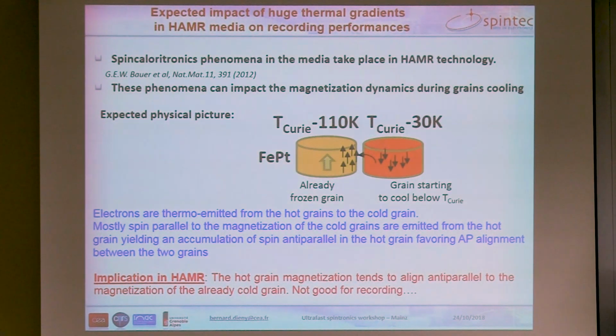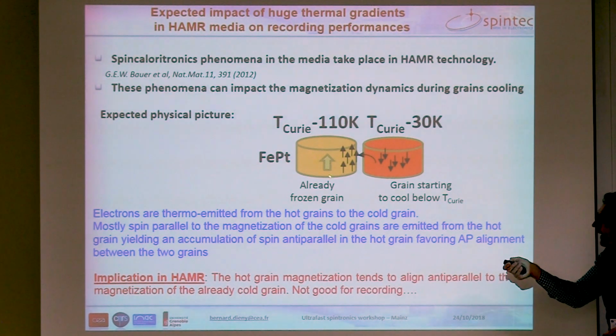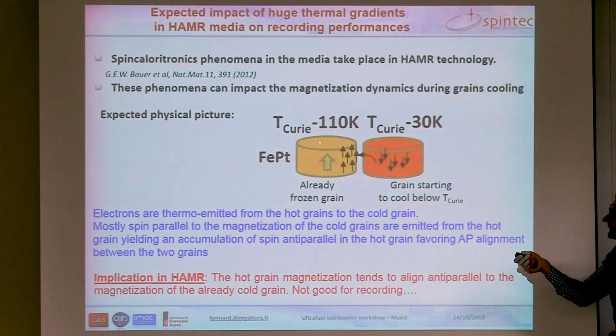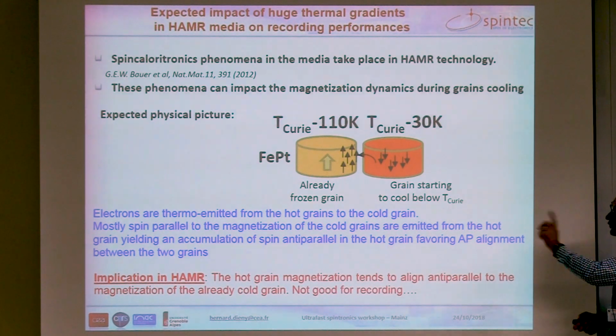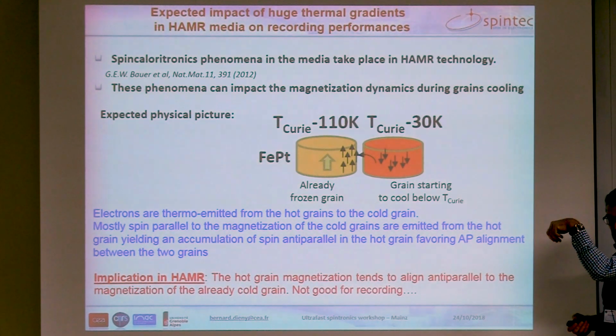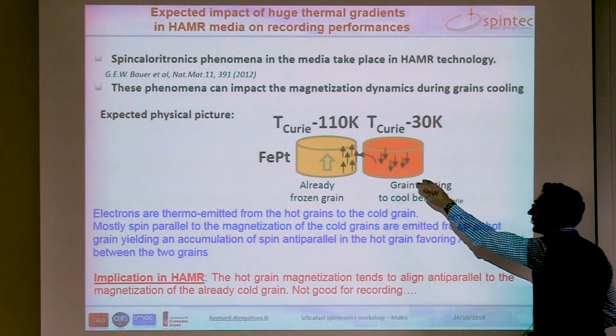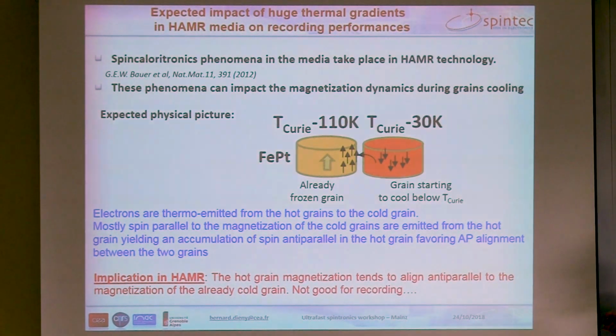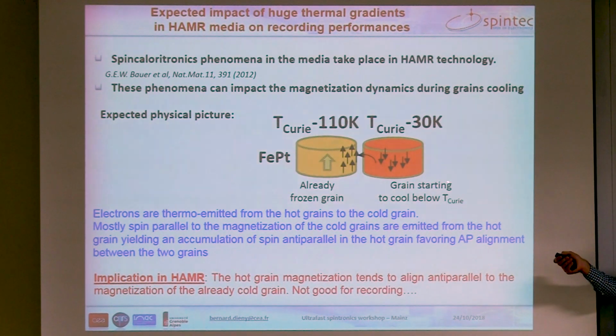Now, because this grain is hotter, it's emitting a lot of electrons, more than this one, and it's emitting both up and down electrons. But because this grain has up magnetization, like in a magnetic tunnel junction, it is going to transmit more up electrons than down electrons. So we are going to accumulate in this hot grain spin down electrons, which are going to favor anti-parallel orientation of the magnetization of this grain with respect to this one.